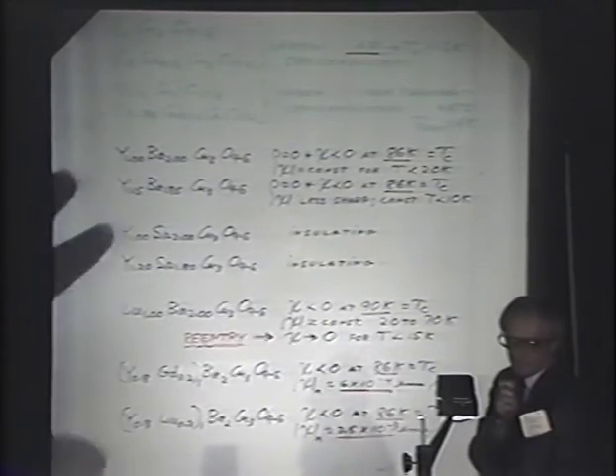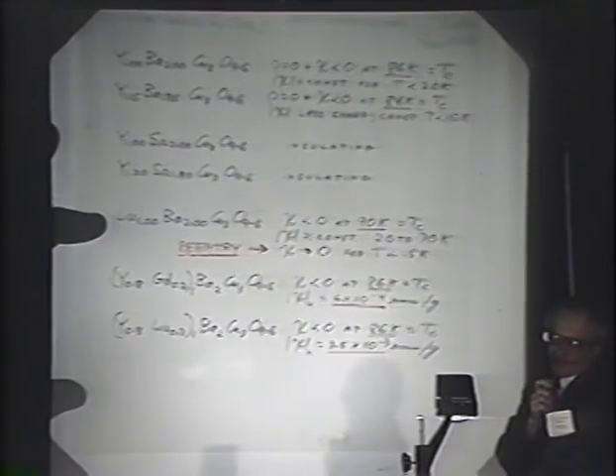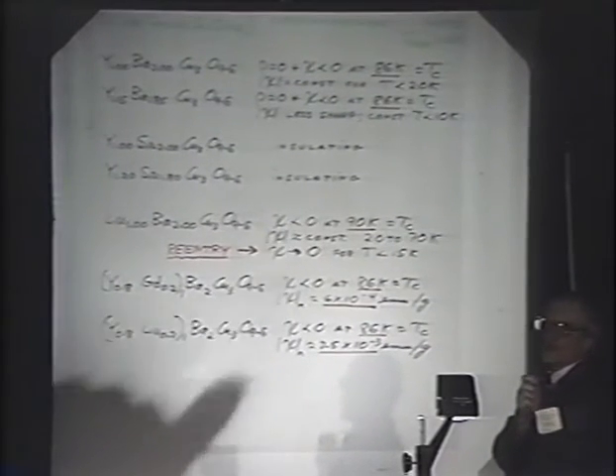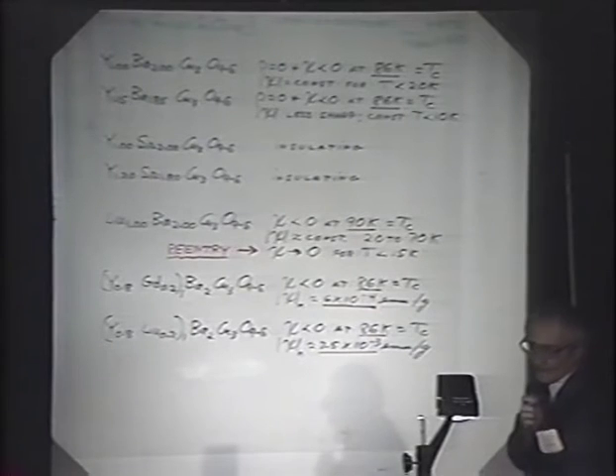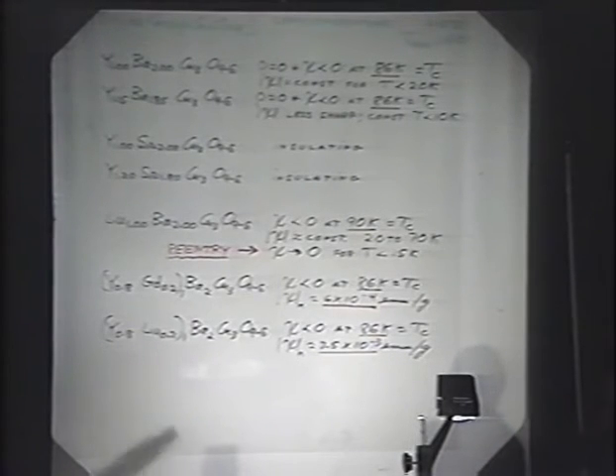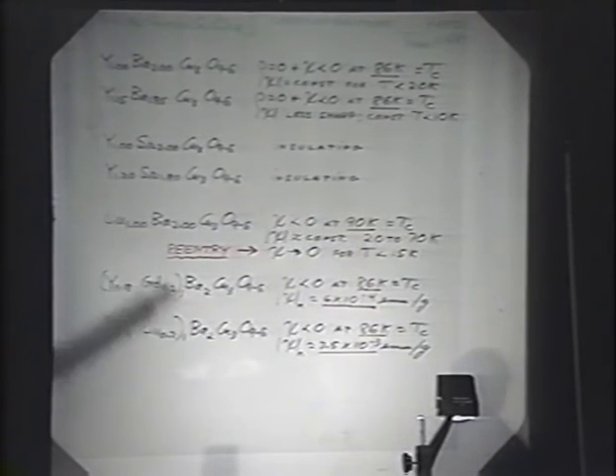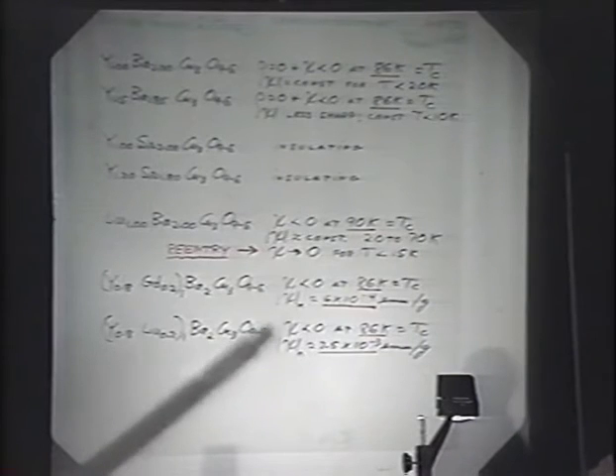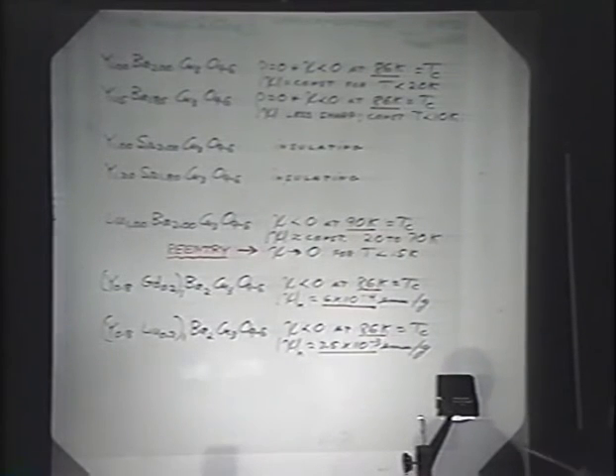We then went on this week and we did a lutetium phase. The superconductivity appeared through its diamagnetism at about 90 degrees Kelvin, and we seem to be getting a very strange low temperature behavior. The plateaus, which I showed on the previous slides, appeared. However, as one went to lower temperatures, in particular below 15 degrees Kelvin, the susceptibility returned to 0, meaning the superconductivity disappeared as we pursued the temperature down to 4.2 degrees Kelvin.